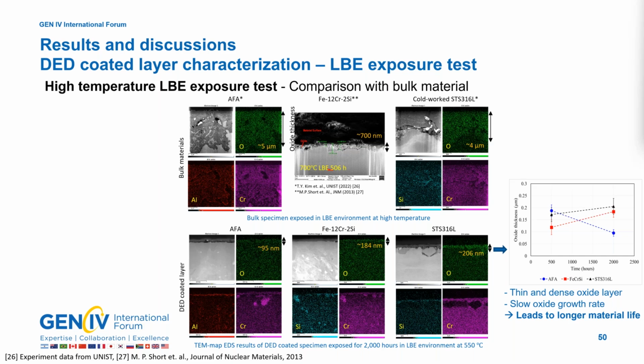Compared with the previous LBE exposure test results performed by other researchers on bulk materials, the DED coated layer shows very thin oxide layers for all powders. Therefore, the oxide layers of the DED coated layer could be more protective in a high temperature LBE environment than bulk materials, leading to a longer material life.